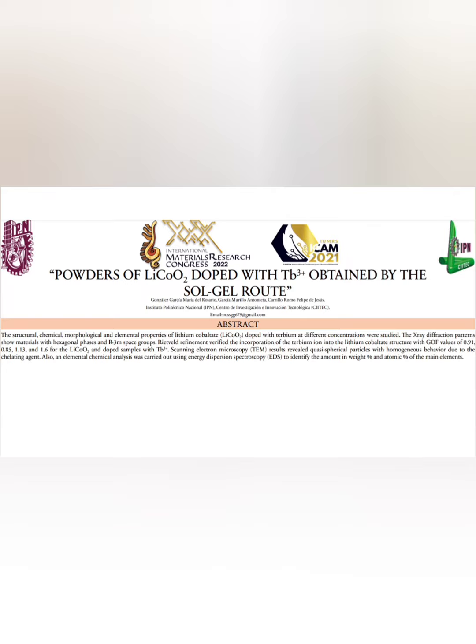The X-ray diffraction patterns show materials with hexagonal phases and the R-3m space group. Rietveld refinement verified the incorporation of the terbium ion into the lithium cobaltate structure, with goodness of fit values of 0.91, 0.85, 1.13, and 1.6 for the lithium cobaltate and the terbium-doped samples.